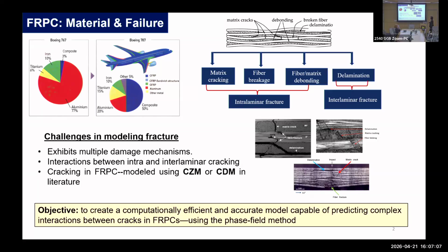matrix viscoelasticity, etc. So in the modeling domain of this complex fracture behavior, of course, characterizing and incorporating multiple damage mechanisms is always a challenging problem in the composite community. More precisely, the interactions between intra to interlaminar cracking has been reported as a big challenge. And those of you who are familiar a little bit with the fracture of FRPC, you probably have heard these two keywords, cohesive zone modeling or continuum damage mechanics approach. Both have been used widely to model cracking behavior in composites.